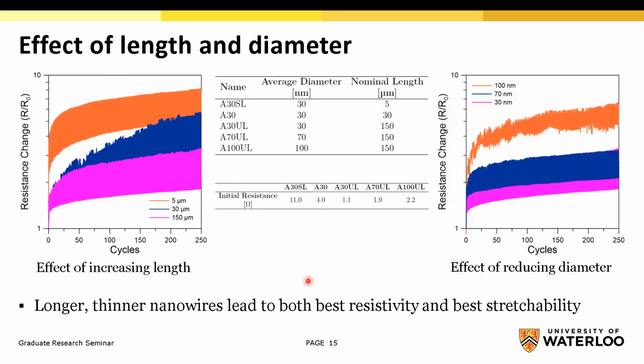Effect of length and diameter. Initially, we investigated the effect of length and diameter of the nanowires in the ink. This plot shows the effect of increasing length, and this plot shows the effect of reducing diameter. To study the effect of length, we used commercial silver nanowires: A30SL, A30, and A30UL. You can see the average diameter and nominal length for the nanowires. All three have the same diameter and different lengths of 5, 30, and 150 microns. For the diameter, we used A30UL, A70UL, and A100UL.